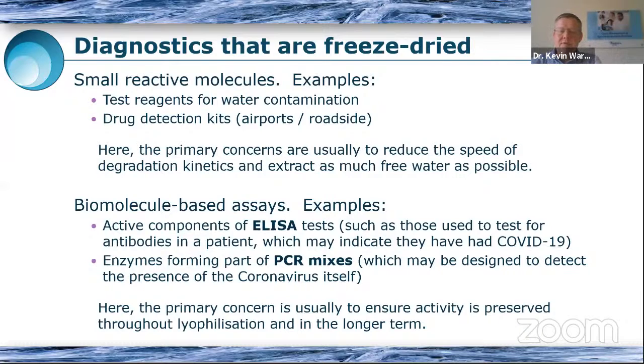And so usually the primary concern here is to take as much water out as possible to reduce the speed of degradation kinetics, and slow down any hydrolytic reactions. And these tend to be quite simple, as long as you don't degrade the small molecule or change it to a completely different molecule, generally that's fine. What we tend to be more concerned with these days, or what we see more of, are the biomolecule-based diagnostics. So in this case, and again, a good current example, COVID diagnostics.